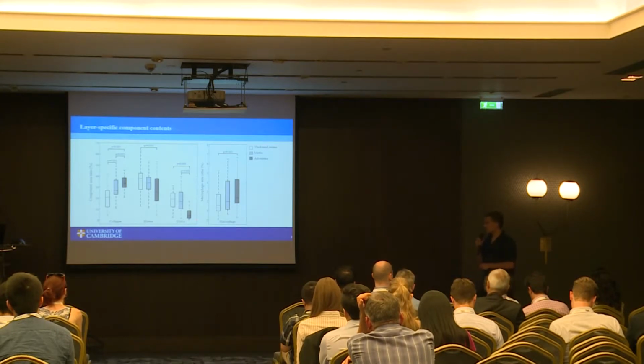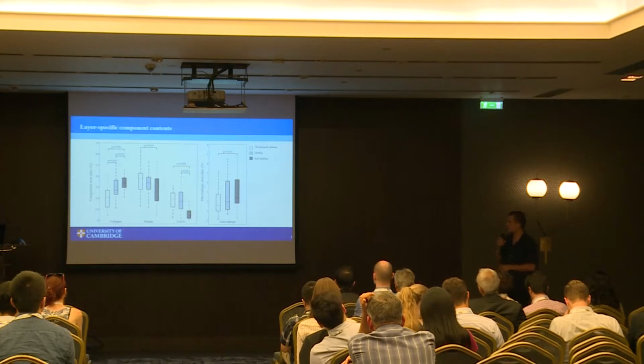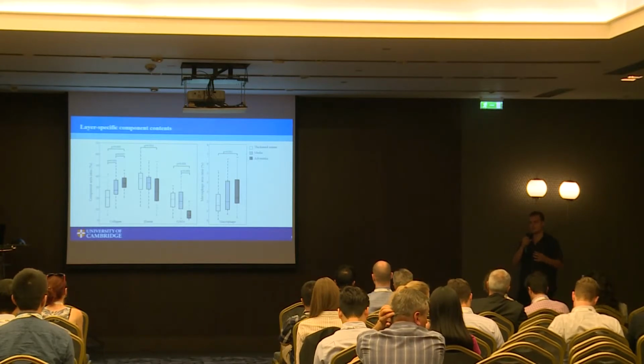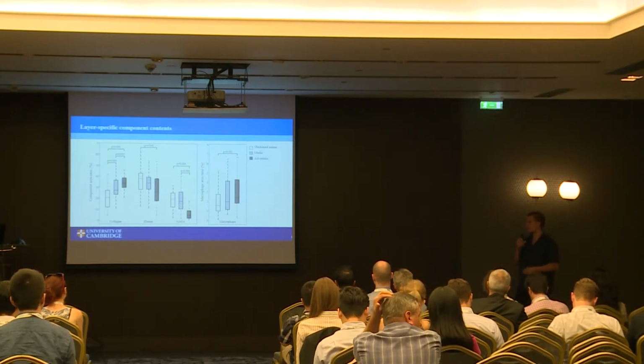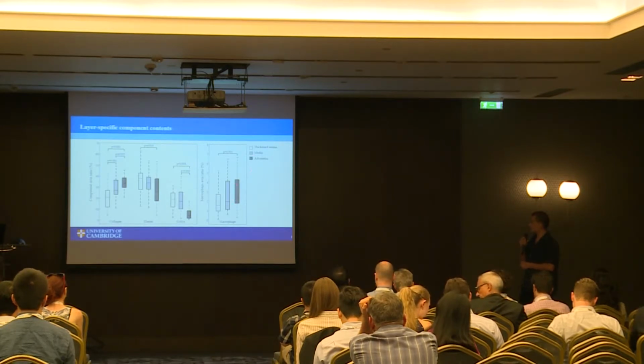But when we look into the GAG content, we saw that although the content of GAG is the same in the intima and the media layers, their GAG content was much larger overall than the adventitia layer. I want to stress at this point that we hypothesized initially that GAGs are a bad contributor of mechanical properties. So with disease, we hypothesized that the GAG content will increase and it will cause the mechanical properties to decrease. We also didn't see too much of a difference amongst the macrophage content except for a larger macrophage content in the adventitia compared to the intima.